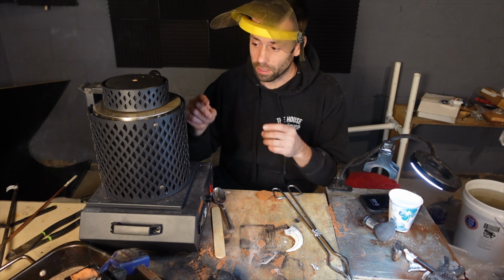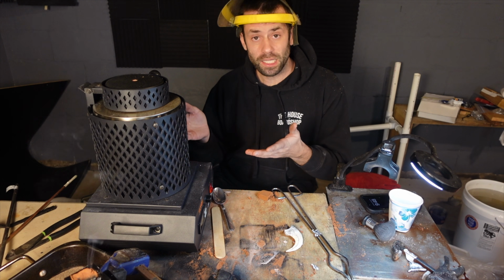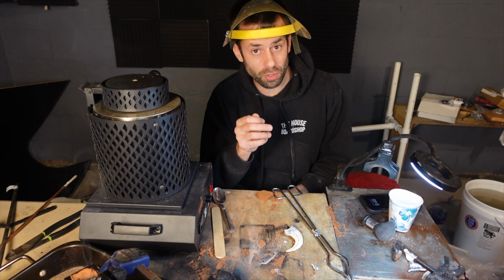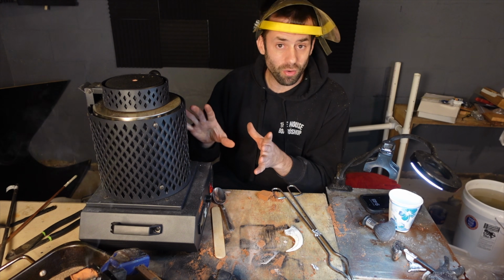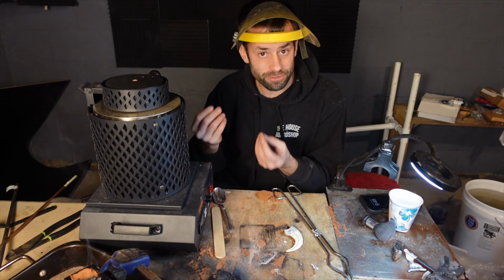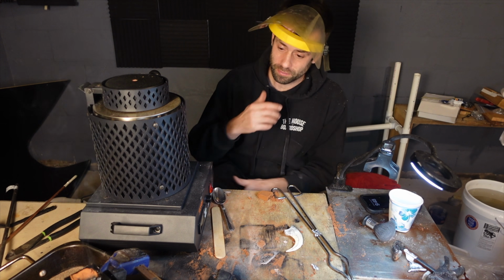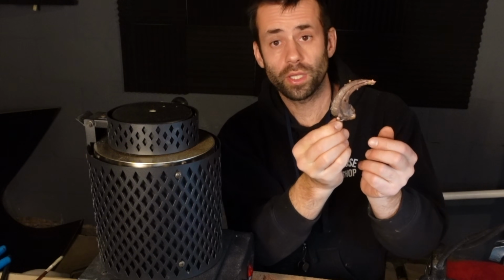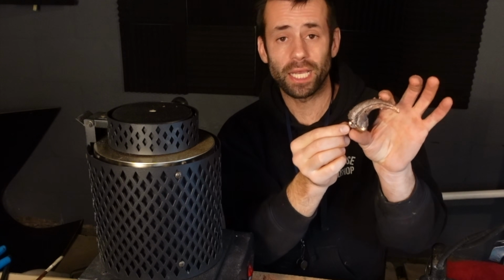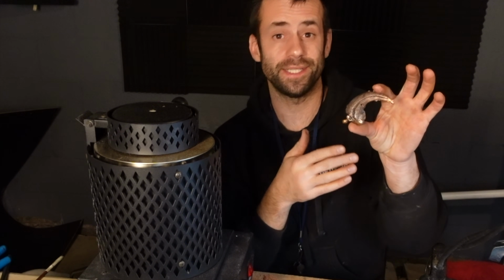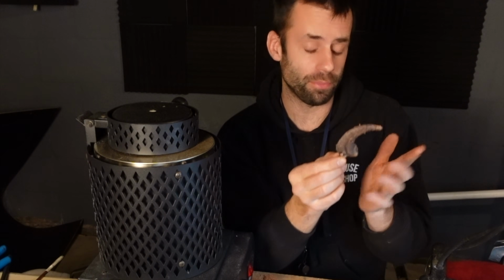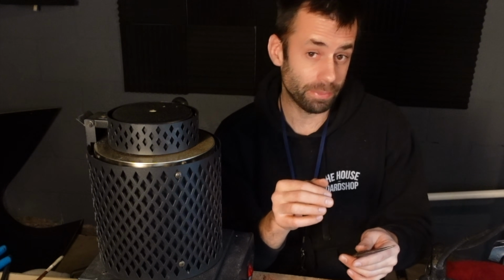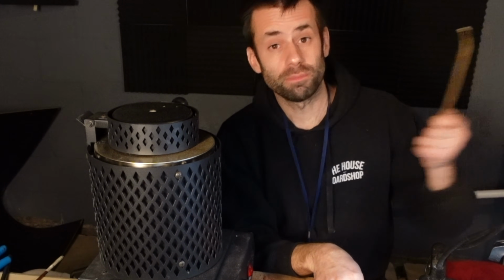This is interesting. The first time I melted it, it did get liquid and I did pour the claw. That looked pretty good. It just broke in half. But now I can't get it to get to that fluid state. I don't know why. So we kind of got a copper claw. Not the best, but copper is notoriously a difficult metal to cast. Pure copper. So I'm going to dial it back a little bit and we're going to test out some bronze.